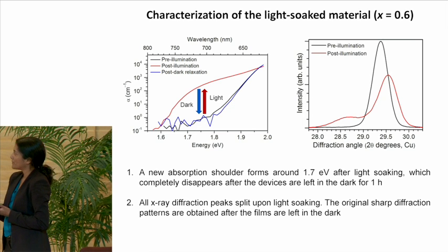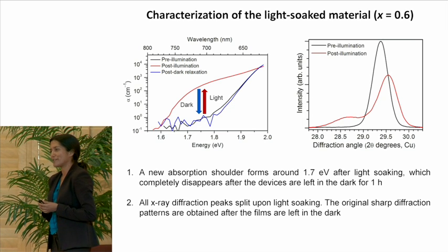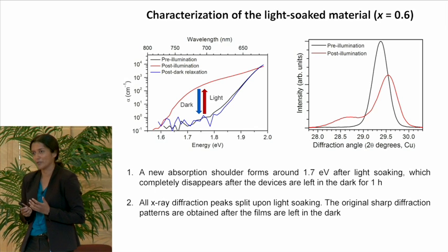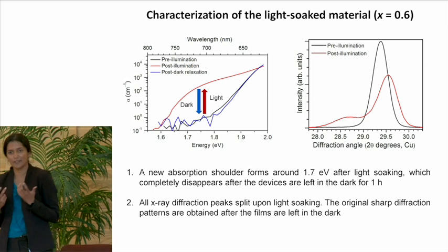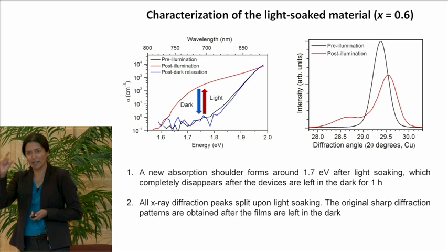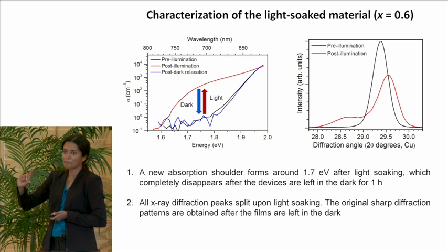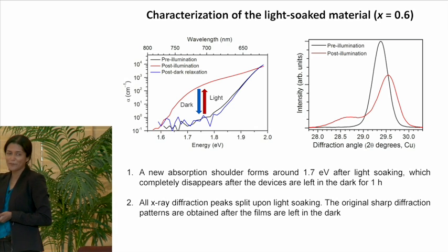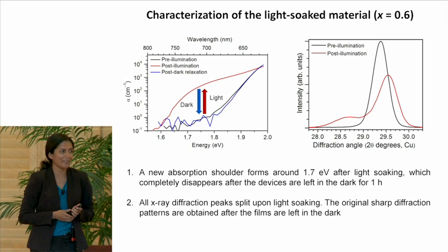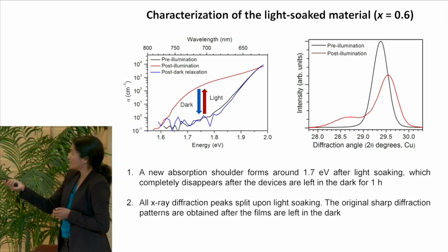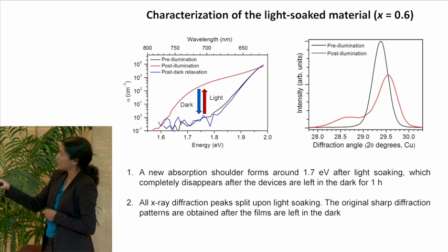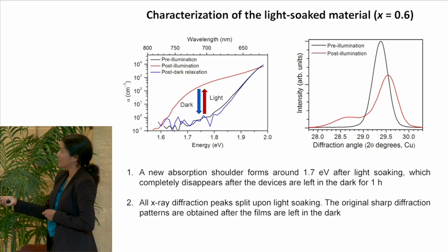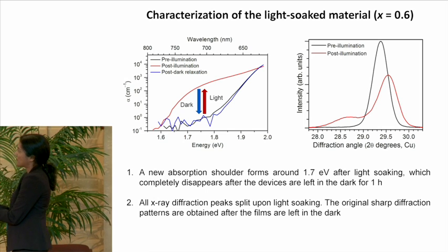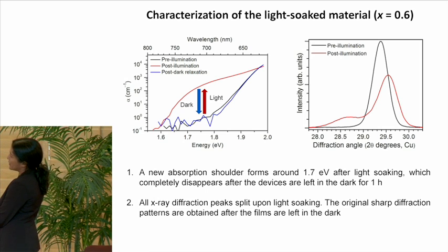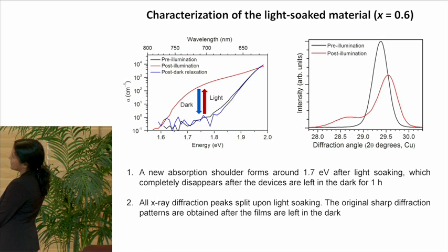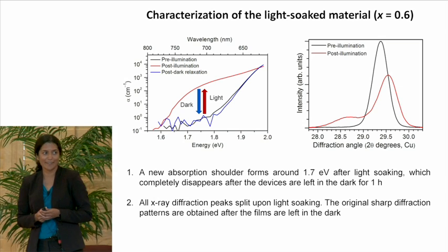And Eric then wanted to study the structure of this material under illumination. So he decided to look at the X-ray powder diffraction pattern of these materials under illumination. So he employed this very sophisticated experimental setup where he suspended a bicycle lamp inside the diffractometer. And he just turned on this lamp, and this was enough to cause a change in the powder pattern of this material. When the light is turned on, he sees that every peak is split into 2 peaks. And when the light is turned off, he sees that the original peak grows back in. And these split peaks show the presence of a material with a larger lattice than the original, as well as a material with a smaller lattice than the original mixed halide perovskite.